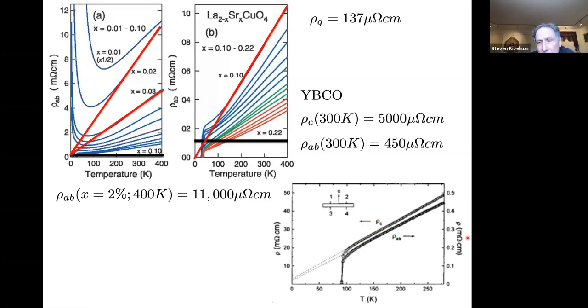The two scales are somewhat different. The resistivity in the C-axis direction at room temperature is something like 5,000 microohm centimeters. Again, 1.5 orders of magnitude bigger than the quantum of resistance.